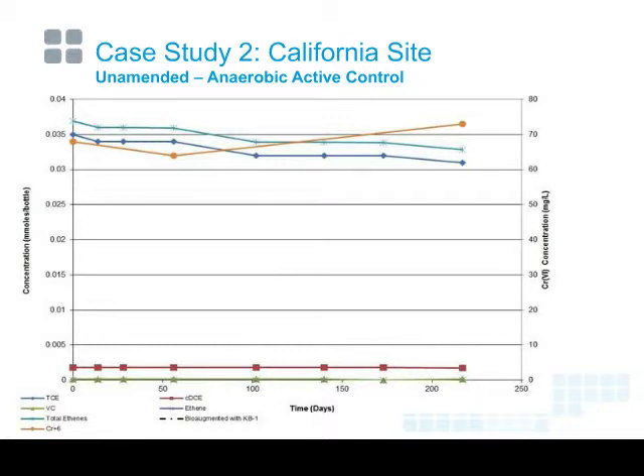And we have the chlorinated ethenes in total millimoles on the left-hand axis, and you see that the TCE showed a very small decline over the incubation period that's within the normal experimental variability of 10 to 20%, which is pretty standard for analytical and experimental variability. And we don't see any significant changes in those over time. And you see that the total mass of chlorinated ethenes is pretty consistent as well.